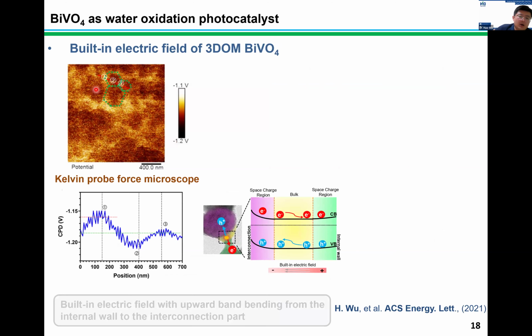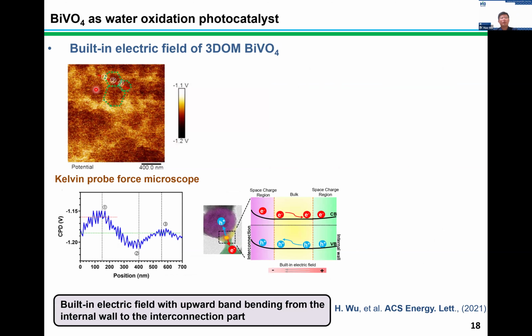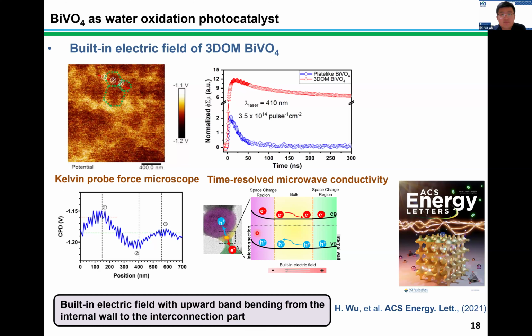And we found that there is a built-in electrical field with an upward bending from the internal wall to the interconnection part. It suggests that the photo-induced holes will be easily extracted to the internal wall, and the electrons will accumulate on the interconnection part. This facilitates the spatial charge separation of photo-induced carriers and contributes to the enhanced charge mobility. To prove that, we also did the time-resolved microwave conductivity measurements, and the results suggest that indeed the 3-dome bismuth vanadate shows an enhanced charge mobility compared to the bulk counterpart, with around 6 times enhancement.